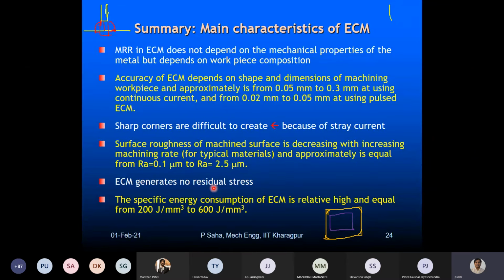This is very important. I think this is one of the few processes which will give you a residual stress free surface. Maybe chemical processes are also like this, like the electrochemical process. That's why ECM is very much used in the aerospace industries, where safety has to be ensured and the fatigue life of the component has to be pretty high. Any sudden failure of the component that may come from residual stress, which may compromise fatigue life, has to be avoided, so particularly turbine blades and other such components have to be residual stress free.